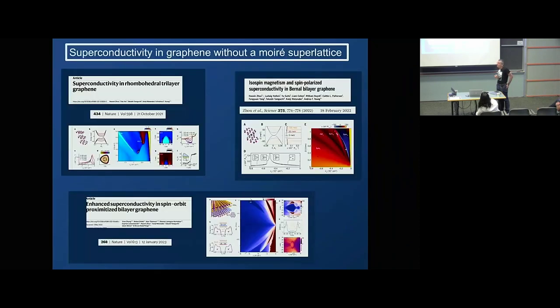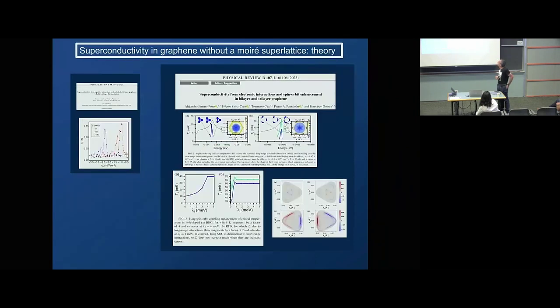Now we went on, there was the discovery of superconductivity in untwisted systems, so we repeated our calculation in the same manner, and we got also superconductivity, but of quite a different character. The superconductivity here, I mean we included everything in the same way, phonons, electron-electron interactions, and so forth. But it occurs at much lower temperatures, and in addition the gap has nodes within each pocket. So that is more what you expect in a conventional, strongly correlated system.